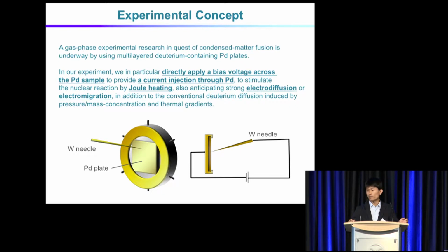In addition to the conventional diffusion induced by pressure gradient or mass concentration gradient and thermal gradient as a driving force, by the direct current injection we can induce a strong atomic movement, so that we can probably induce a higher stimulation force, because we know the strong dynamics of the atoms as well as probably electrons are very important to induce this kind of reaction we are focusing on.